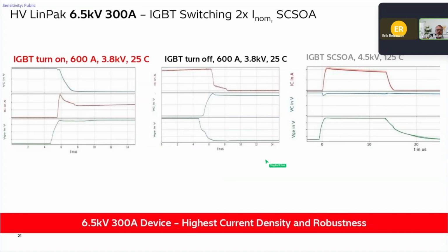We also have, of course, the housing for the higher voltage devices. So here is an example of SOA conditions, IGBT turn-on, turn-off, short circuit. For a 6.5 kilovolt device, we will rate this 300 amp. And here we see also quite a robust chip. In this case, it would be a planar chip, but very robust, and the highest current density that we see out there.